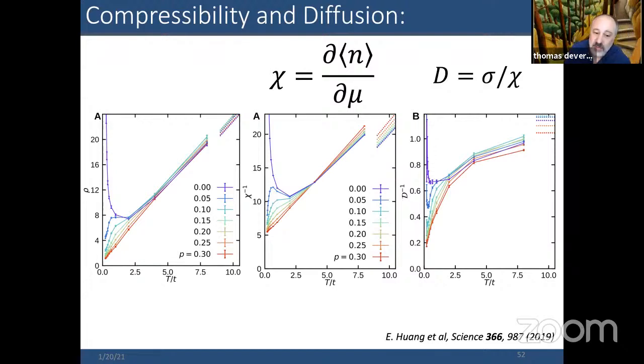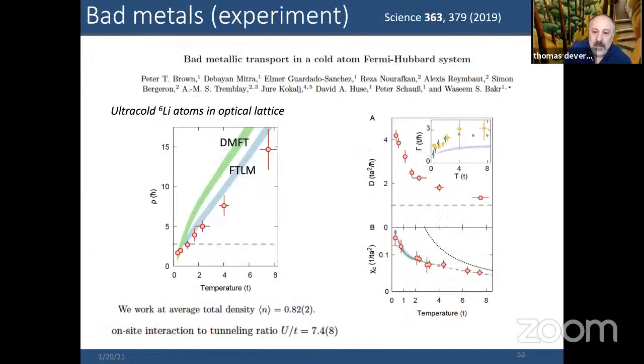So we see the linear in T dependence really involves a trade-off between the compressibility and the diffusivity, and gives the apparent continuation from low temperatures all the way up to high temperatures. And I think it was shown in Antoine's talk that this type of behavior can be measured in a cold atom system, and the diffusivity shows exactly this behavior of having a constant value at larger temperatures, which grows with decreasing temperature, or one over the diffusivity, which decreases as temperature goes down, with the compressibility giving the resistivity